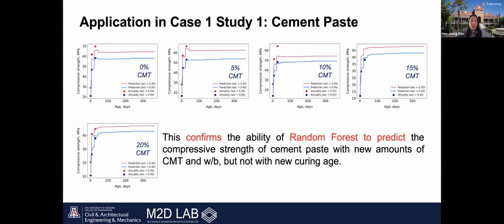And the random forest model trained using our case one data, which predicts the compressive strength of cement paste with a new amount of copper mine tailings and water to binder ratio, was used to generate a predictive compressive strength curve over curing age. And in the graph, the points represent the experimental data, which are the actual values, and the line represents the model's predictions. And the results confirm that our machine learning model can accurately predict compressive strength for new CMT contents and water to binder ratios, but it doesn't perform as well when predicting new curing ages. And we also expected the compressive strength to continue increasing after 28 days, but the predicted curve shows a plateau, meaning the model assumes the strength stays almost constant after 28 days.